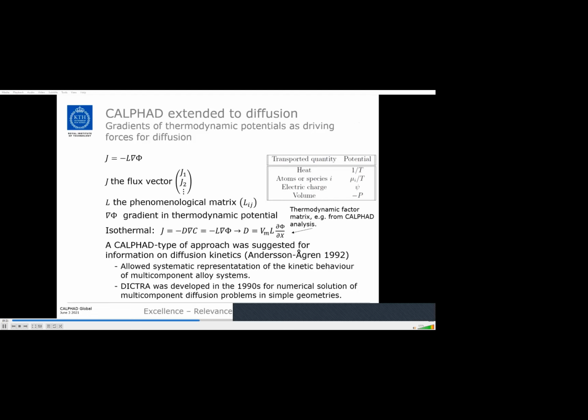Well, in that case, gradients of thermodynamic potentials serve as a driving force for diffusion, and we can write it in this simple way. The diffusive flux is equal to minus some coefficient times a gradient in the thermodynamic potential. And actually, those quantities are vectors and matrices. So this J is a vector containing the flux of number 1, number 2, and so on. And then this L is a matrix, usually called the phenomenological matrix. And this quantity is a gradient in thermodynamic potential. And here you can see for the transported quantities, what the corresponding thermodynamic potential is. So for heat, it is 1 over temperature, and for diffusion of atoms or species, it's their chemical potential divided with temperature, and so on.